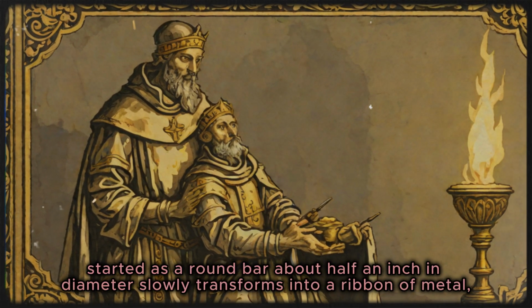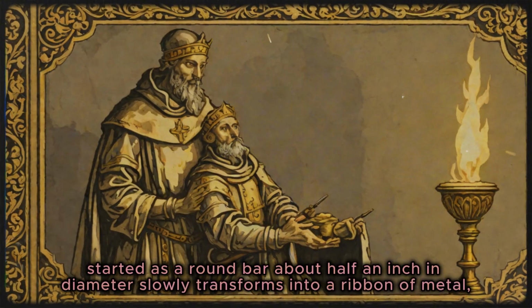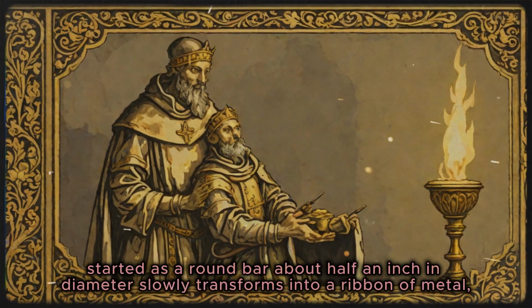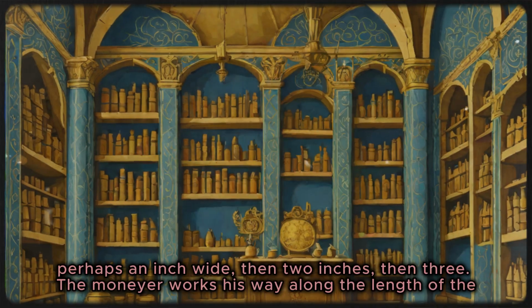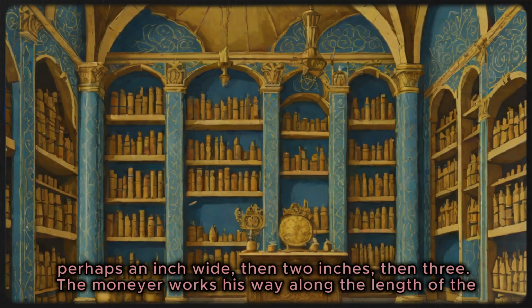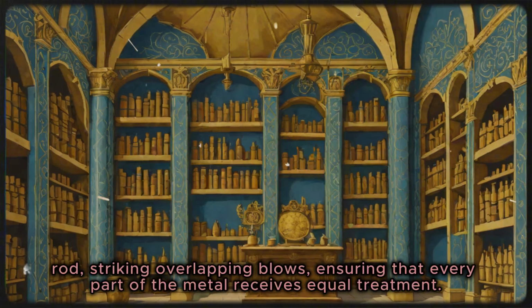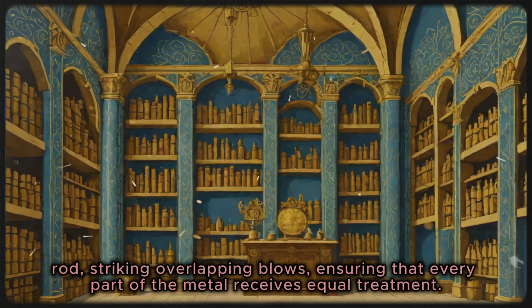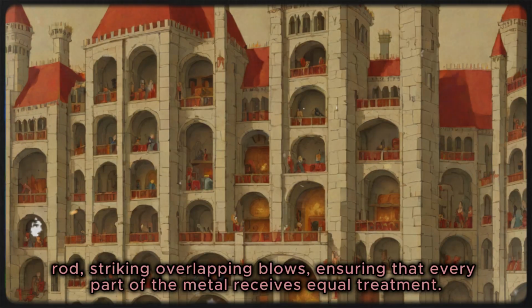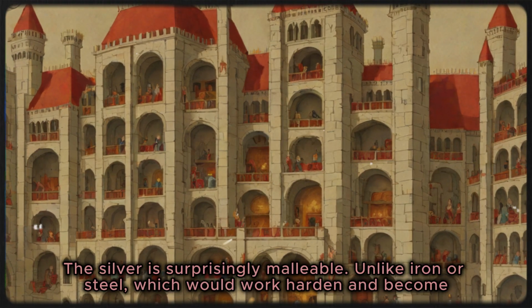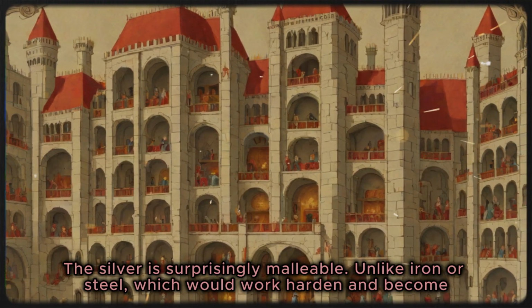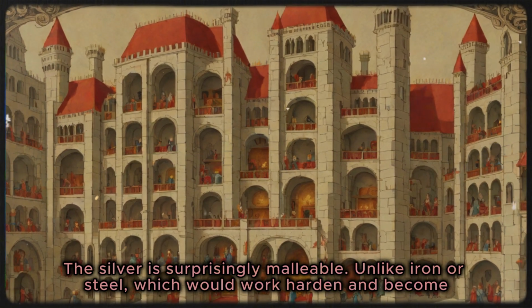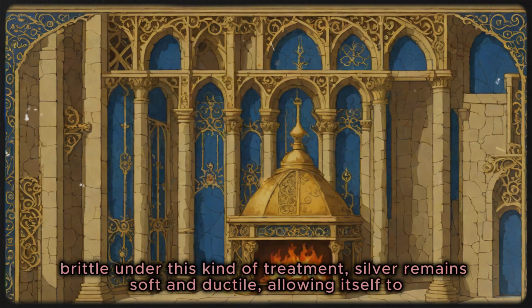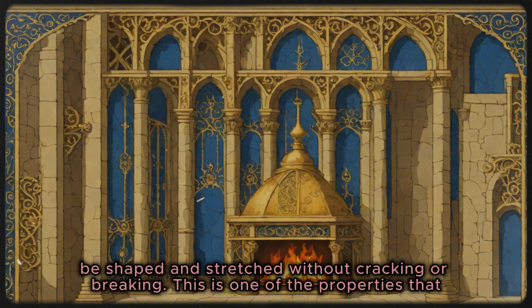What started as a round bar about half an inch in diameter slowly transforms into a ribbon of metal, perhaps an inch wide, then 2 inches, then 3. The moneyer works his way along the length of the rod, striking overlapping blows, ensuring that every part of the metal receives equal treatment. The silver is surprisingly malleable. Unlike iron or steel, which would work harden and become brittle under this kind of treatment, silver remains soft and ductile, allowing itself to be shaped and stretched without cracking or breaking.